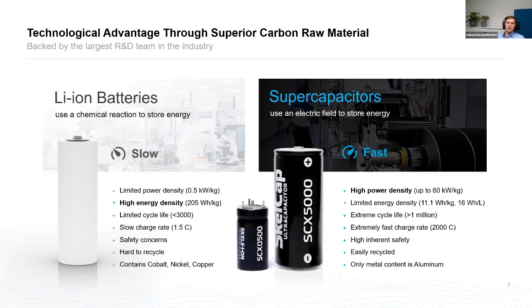So if you look into the properties of the devices, then lithium-ion batteries, of course, because you store these charges in the bulk material, have quite high energy density compared to supercapacitors, around 20 to 30 times higher, depending on how you look at it, which materials you choose, even up to 35, 40 times higher if you choose the really, really new lithium-ion batteries that are now coming onto the market. But they have very limited power density, and that also makes sense because you need to move these lithium ions out of these electrodes and out of these material agglomerates into the electrolyte and then over to the other side.